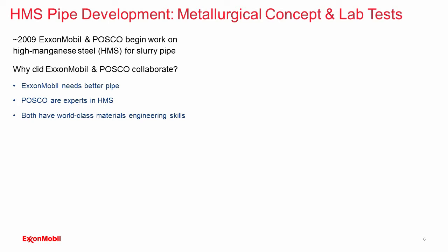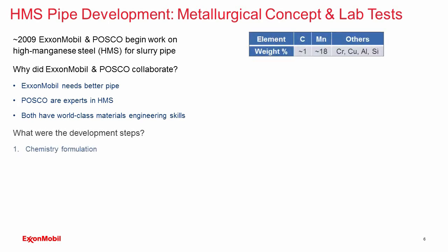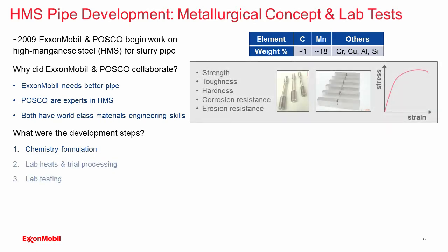Here is a general idea of the development steps. First, the chemistry formulation. The chemistry is about 1% carbon, 18% manganese, and a number of other alloys. Chrome you can see there for the corrosion resistance. And we conducted a lot of laboratory trials, made many lab heats, studied the processing, the heating and cooling, and the rolling of the material, and then measured basic properties like strength, toughness, hardness, corrosion, and erosion resistance.